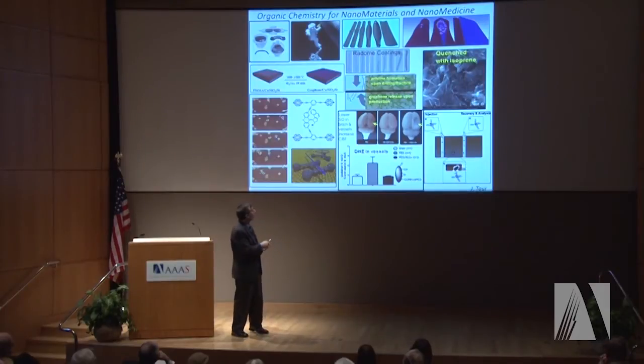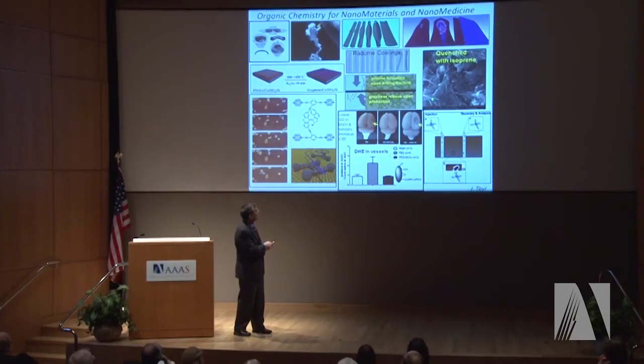We also took potassium with multi-walled carbon nanotubes and heated them to 250 degrees with no solvent — just potassium metal and the nanotubes. The potassium will intercalate and then rip them open and split them longitudinally, which turns out to be really nice for very conductive ribbons. All across the edge you get potassium, giving you an aryl anion — a site for polymerization. You just add a vinyl monomer and do anionic polymerization right across the edges, so polymer grows off all the edges. You get these very conductive sheets with polymer off the edges, which is tremendous for applications where you want tough materials — plus now they're conductive — giving you conductive rubber and conductive plastic materials.